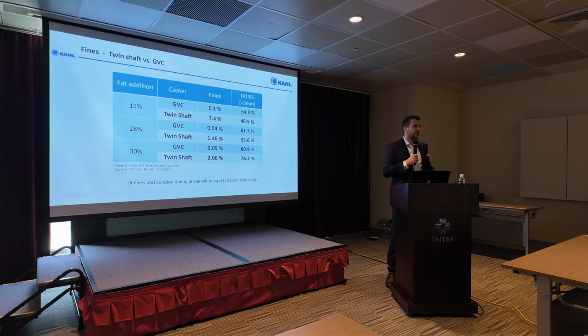So basically it means for different mixing times. And when you compare the results, you see that depending on the mixing, we have roughly 7% less fines produced, or with the lowest fine difference, roughly 1.4% difference.